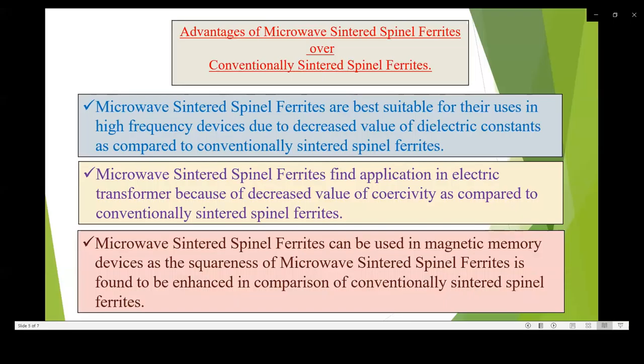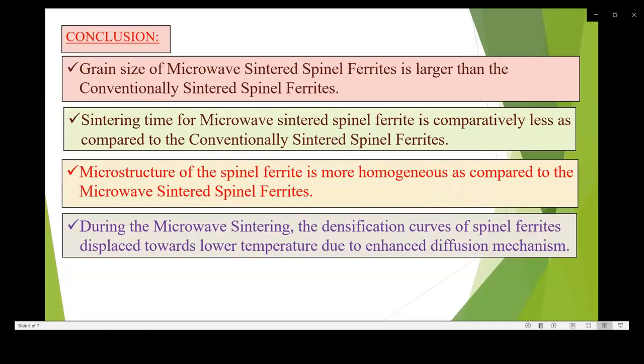Here are the conclusions. Grain size of microwave sintered spinel ferrites is larger than the conventionally sintered spinel ferrites. Sintering time for microwave sintered spinel ferrite is comparatively less as compared to the conventionally sintered spinel ferrites. Microstructure of microwave sintered spinel ferrite is more homogeneous as compared to the conventionally sintered spinel ferrites.